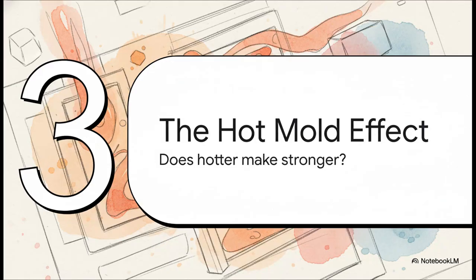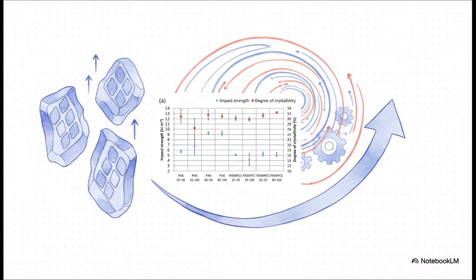Okay, let's get to the good stuff, the results. And we're going to start with the variable that it turns out made the biggest difference of all, the temperature of the mold. So does a hotter mold actually make for a stronger plastic? And the answer is a huge, resounding yes. I mean, just look at this chart. The blue diamonds show the impact strength, which is just a measure of toughness. See that massive jump between the first 2 points and the next two? That's the hot mold at work, boosting toughness by up to 60%.